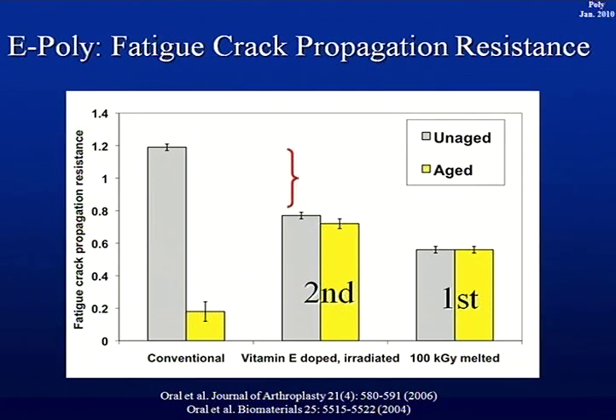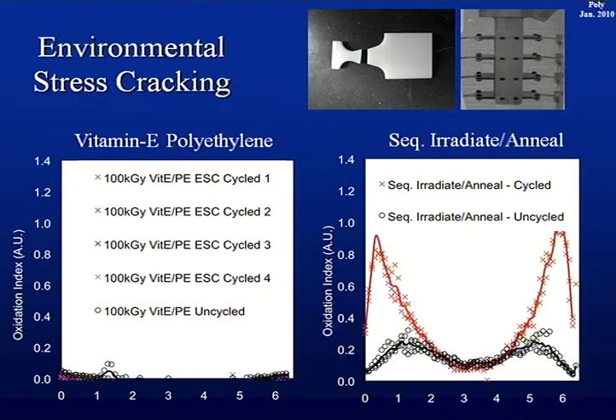The fatigue crack propagation resistance, which is the measure of the mechanical strength, conventional unaged is high, but when it gets aged, oxidated, it goes down. Second generation vitamin E doped, irradiated, doesn't matter if you age it. You age it by boiling it in pure oxygen for 5 days. That's a really tough and maybe unrealistic aging procedure. And this is the first generation remelted longevity. So you can see we have improved the strength, but we're still not as high as up there.